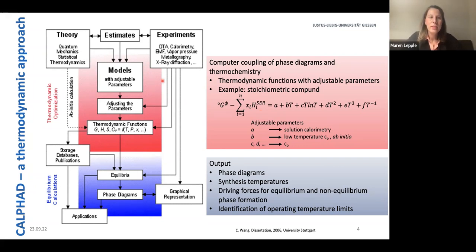And now within the Calphad method, these adjustable parameters are fitted to experimental data, for example, thermal analysis data, calorimetry data, phase diagram data, and so on. Or if they are not accessible experimentally, then also estimates or theoretical data are used, for example, DFT or ab initio data. And then these adjustable parameters, A, B, C, and so on, are fitted to this data.